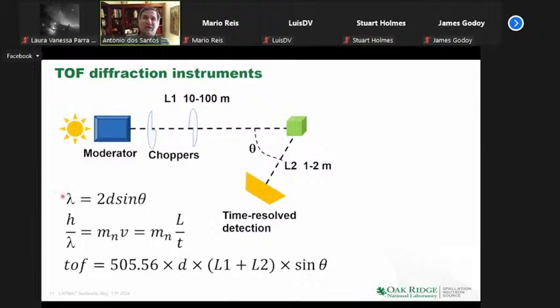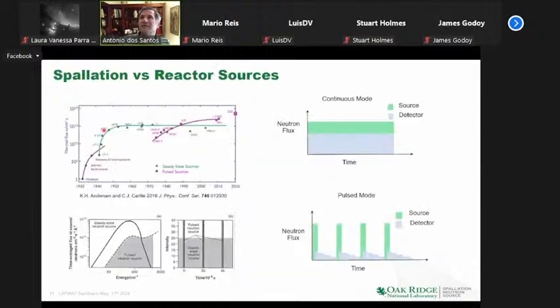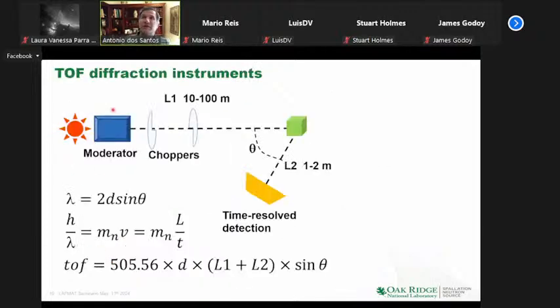Of course, you start with the same Bragg's law, but then you have a pulsed source, and a moderator that adjusts that energy spectra. Sorry to go back, if I can. This energy spectra depends on the moderator. Where you want your energies to be, you can adjust that by basically putting a box of a material, which can be cryogenic hydrogen, water, or methane, and that will slow down the neutrons so that you have a peak intensity at the energies that you want your instruments to see. So that's what this moderator box is doing. It's just adjusting that wavelength band.